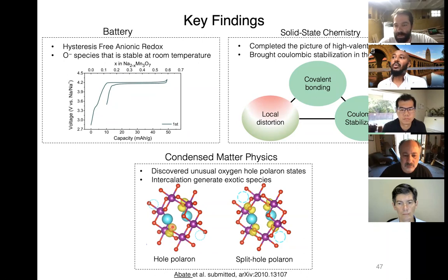So one thing we were able to do in this work is that it really depends on the voltage window you are playing with and the stability of the environment around it. The goal here was trying to understand and discover this species while avoiding all these noises like CEI formation or side reactions. We did a very careful job where we tried to create a very clean surface, but also to narrow the voltage window, thereby avoiding any side reactions, CEI formation, that affect the results. Because what we were hoping for is to see this species in the clearest fashion possible. So that's the work that I have done so far.